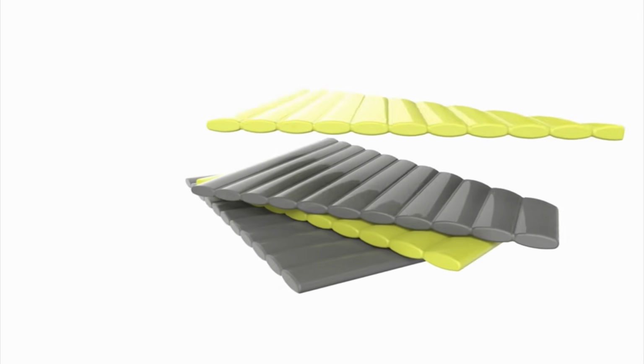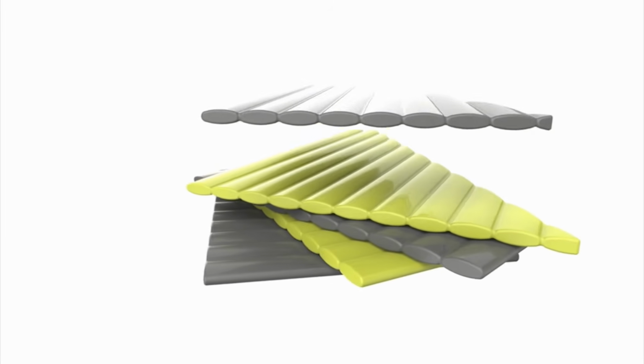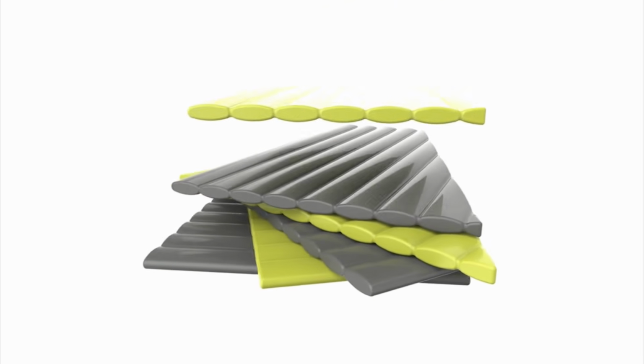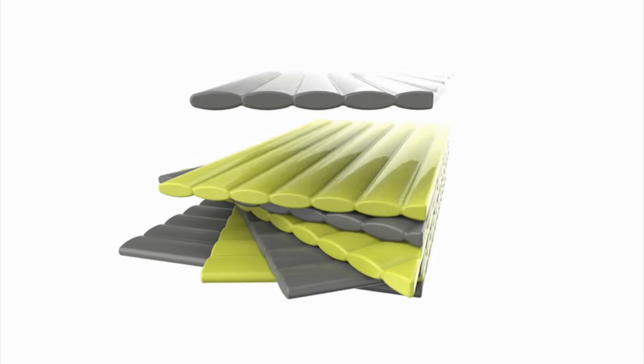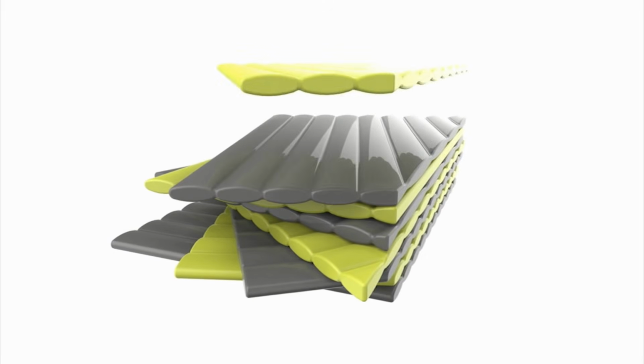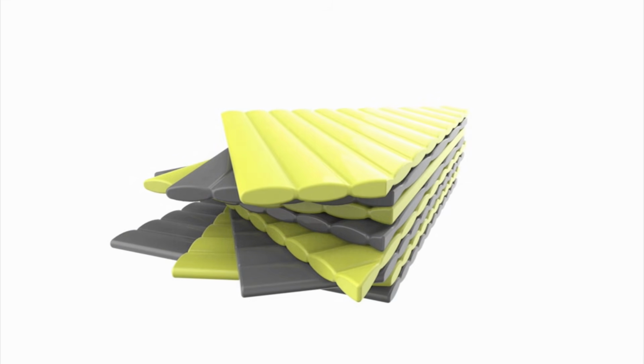So if you look inside the club, you will see that this is in fact a fiber-reinforced composite structure. It's made out of unidirectional layers which are slightly rotated with respect to each other to form this helicoidal distribution of fibers. So we are mimicking that, and we initially deployed that solution for improving impact performance of a wide range of applications, from aerospace, automotive, and so forth.